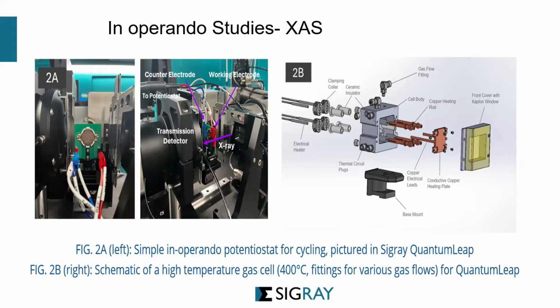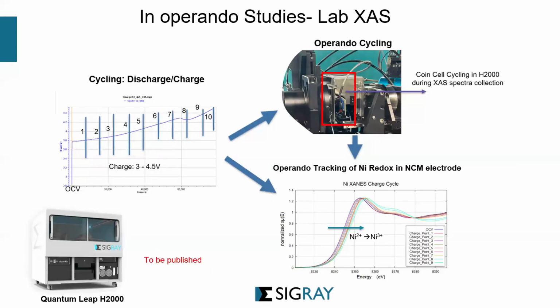We have built operando cells that can run at high temperature or under different types of conditions. So here is the latest study that we have done in operando using our laboratory system, going through 10 charge-discharge cycles and tracking them. And you can see that we can do that in a coin cell under all the cycling modes, and at the same time collect our XAS data. And you see there is a notable shift as it goes from 2+ to 3+. So that study will be published.